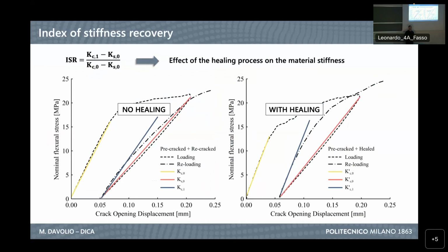And the ones I already described are the non-destructive measurements. Then we move to the destructive parts. As I said, the specimens were pre-cracked and then, after exposure, were tested under failure. For the ones that were tested under 4-point bending, we have this curve, which is the pre-cracking, and the subsequent curve, which is the failure. And from this, we could calculate the index of stiffness recovery, which is defined here. Because, as you can see, this is one case without healing, and the stiffness has no significant variation between the initial loading and the second loading, while when the initial loading is at the beginning and then we have healing, we have a slight or remarkable increase of the stiffness.